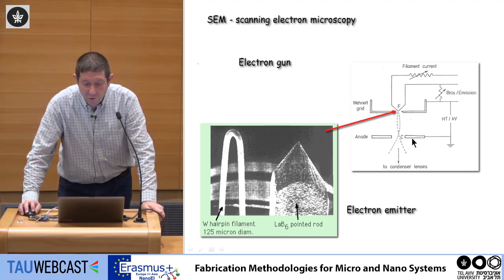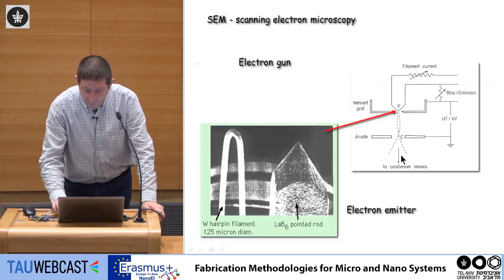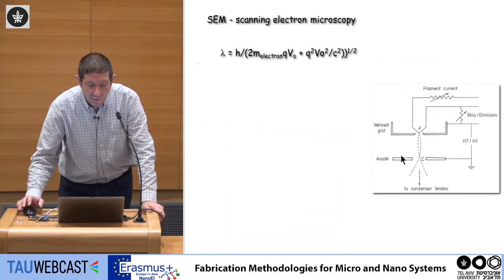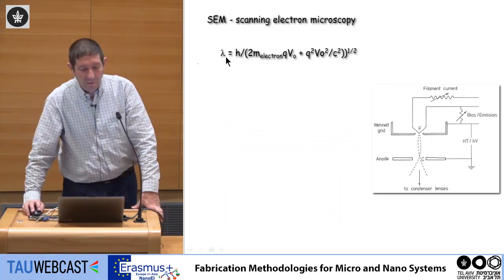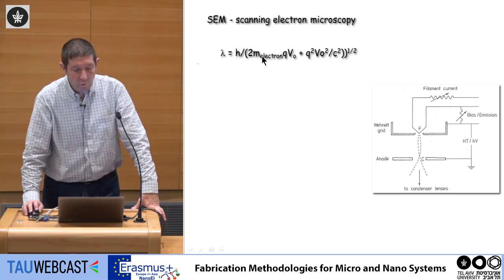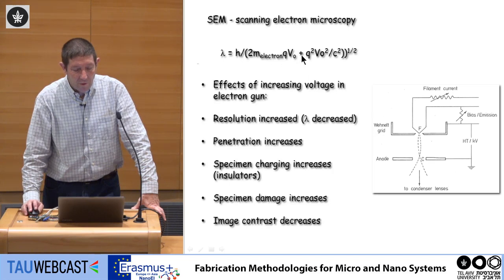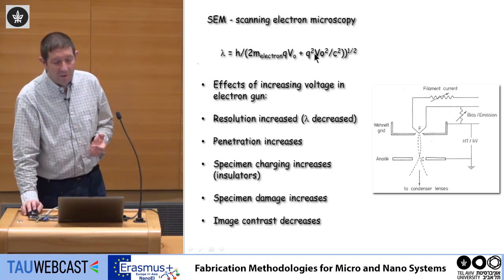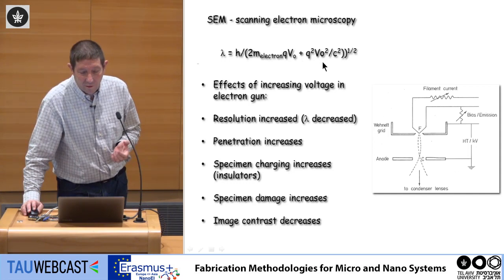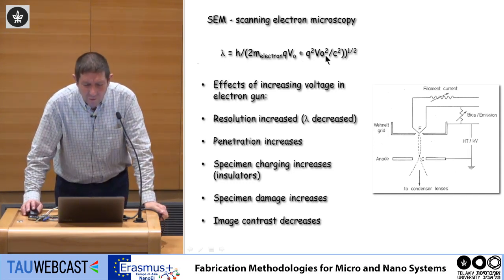You apply a voltage between the anode and the cathode, and you accelerate the electrons. In normal emission, they are emitted at a certain angle, and they are collected through the aperture. And here you need to put a lens to collect them. So this is lambda, the wavelength: h, the Planck constant, divided by the square root of 2 times the mass of the electron, q times V0, which is the accelerating potential, plus the relativistic part, q squared V0 squared divided by c squared.